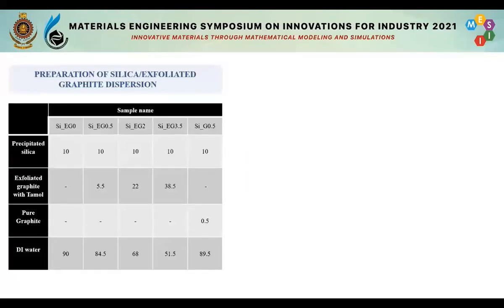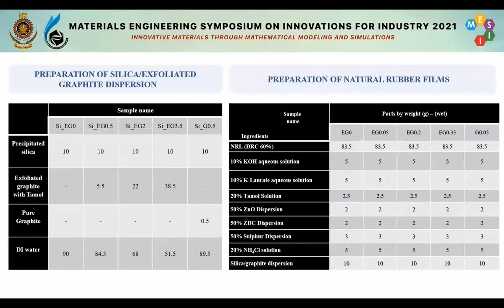In preparing aqueous dispersions of silica and exfoliated graphite, we tried out three different mass ratios of 0.5%, 2%, and 3.5%, and also we prepared a dispersion with just graphite and silica to understand whether the exfoliating of graphite has been effective. By using these 5 dispersions, we prepared 5 different latex films to be characterized and evaluated. As you can see in these compounding formulas, we used all the other additives at the same mass ratios, while the silica and graphite dispersions had different percentages of exfoliated graphite and graphite.